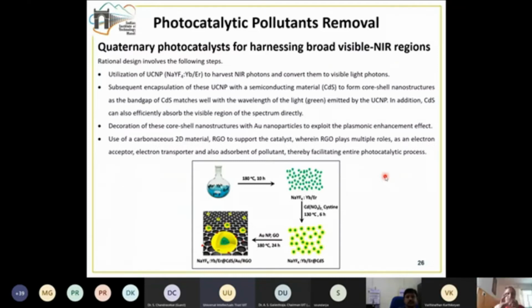Then, in order to further enhance it, we decorated this material with gold nanoparticles, because the gold nanoparticle will have the plasmonic enhancement effect. So when visible light radiation is incident, this will show the plasmonic enhancement. So it will be much better. Then, based on our previous experience, we also took reduced graphene oxide, because the reduced graphene oxide plays multiple roles. It plays the role of an electron transporter because of its conducting nature. It plays the role of an adsorbent for the pollutant, thereby facilitating this photocatalytic process.